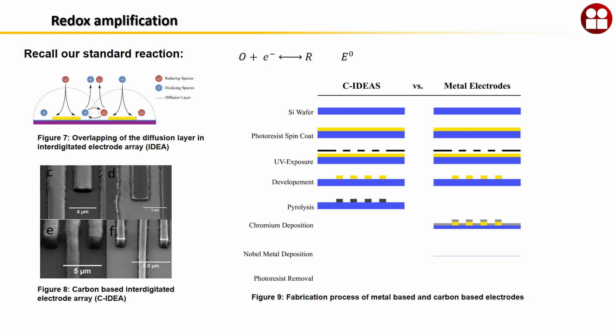I still need to deposit chromium because gold or platinum is not going to stick to SiO2. And then I still, after that, I need to add the layer of gold. And after that, I need to remove whatever I don't want. These 2 steps, they are performed in high vacuum processes, E-beam, thermal metal evaporation, and these are extremely costly. Plus on top of that you're using gold and platinum. This whole system is much more expensive.